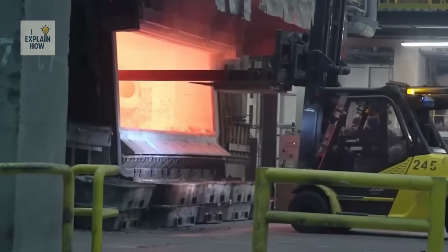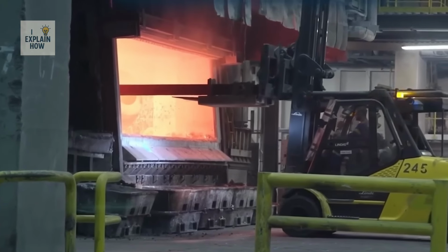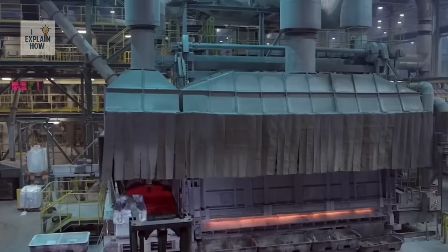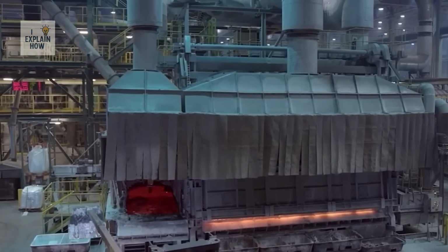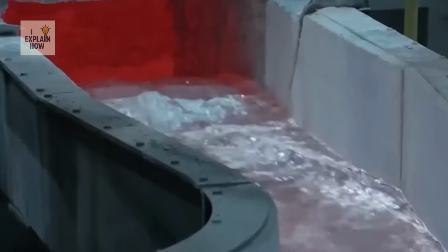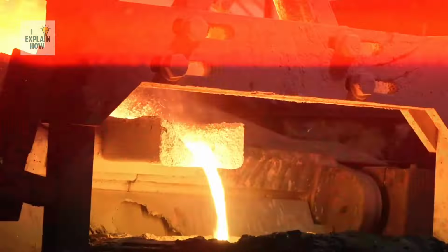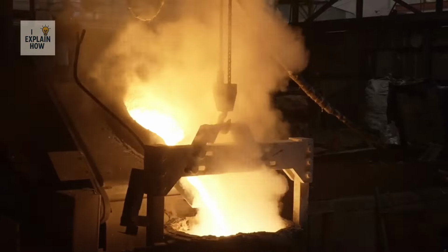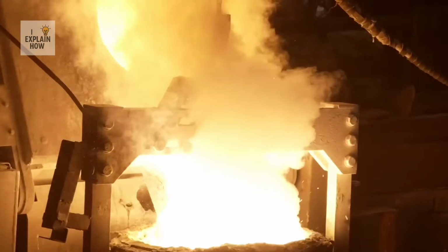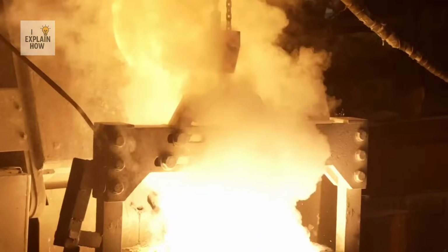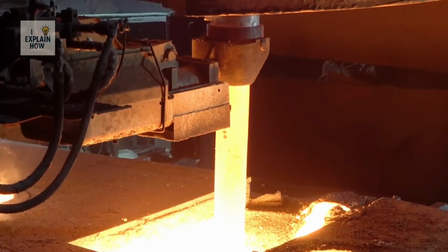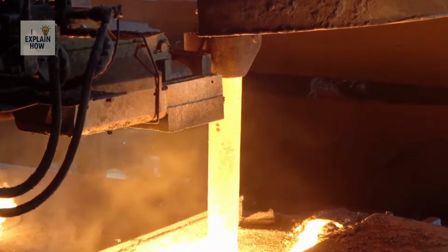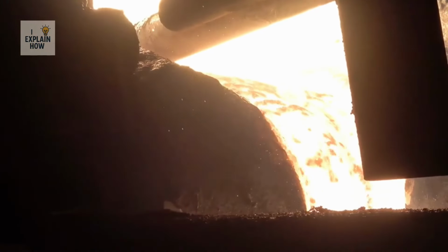Hot and molten, they absorb impurities, forming a layer of slag, while jets of oxygen burn away unwanted elements. Sensors and spectrographic analyses continuously monitor the composition to ensure a perfect alloy. From a chaotic heap of worn parts, now emerges a glowing sea of pure steel, ready to be cast into semi-finished products. The refined liquid steel is immediately conveyed to the continuous casting line.